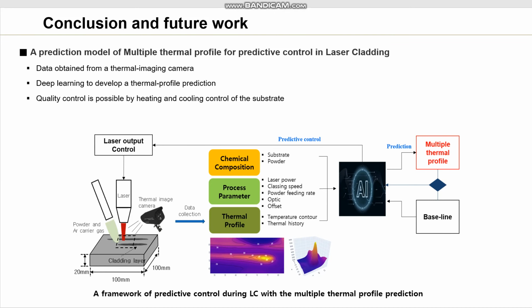The purpose of this study was to develop a multiple thermal profile prediction method for predictive control during the laser cladding process. The thermal profile prediction model proposed in this study accurately predicted the temperature distribution of the substrate and the heat affected zone. So, quality control is possible by adjusting laser output. So, we can prevent product damage by minimizing the time for which the heat affected zone is overheated.